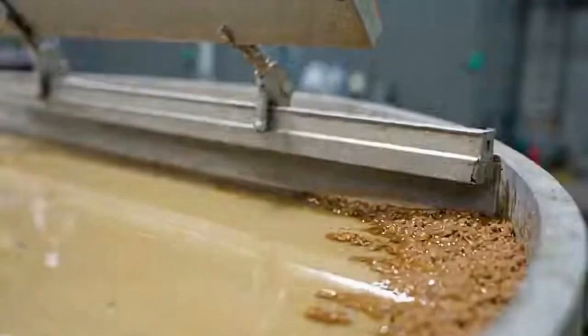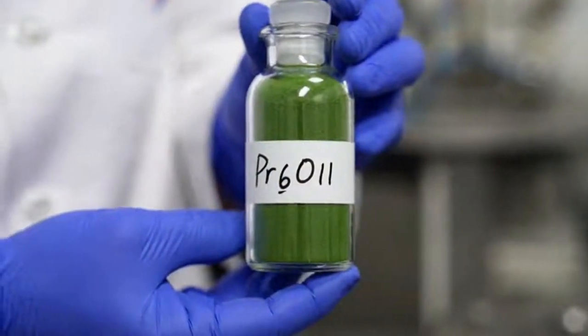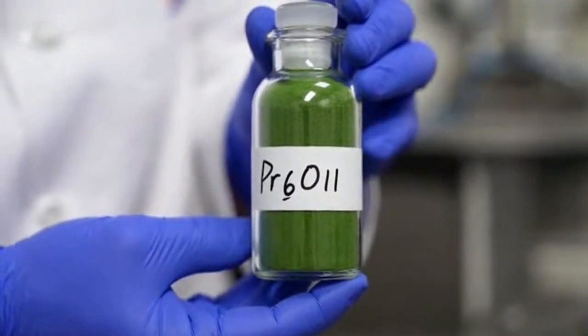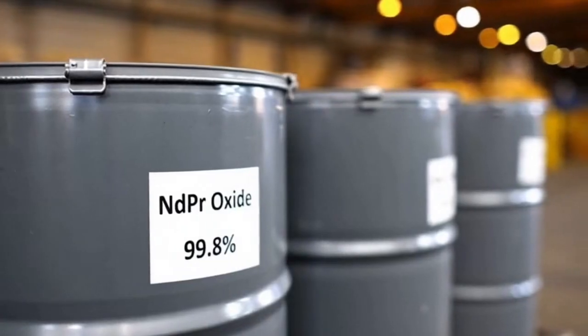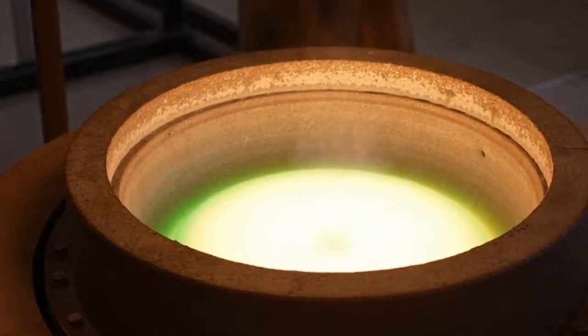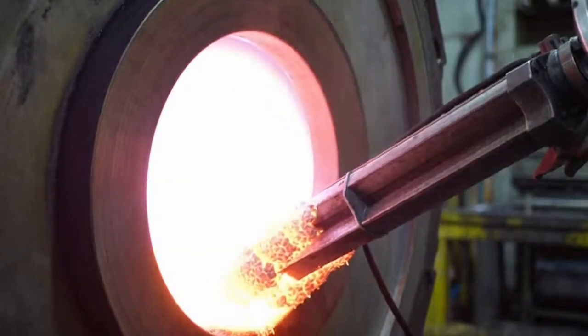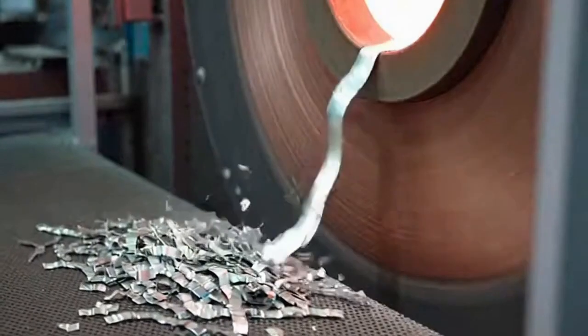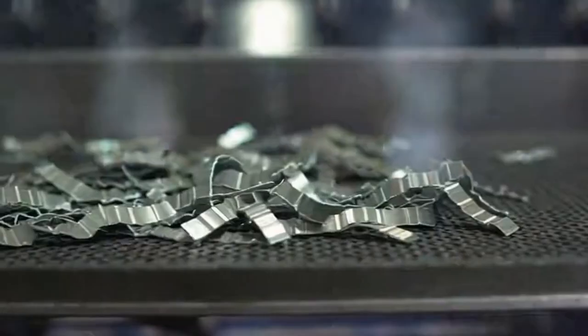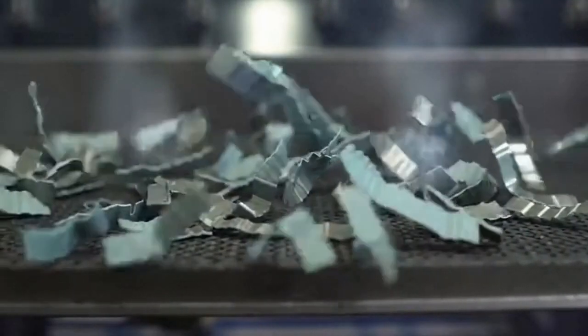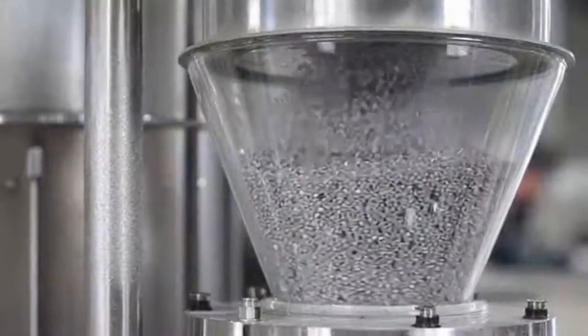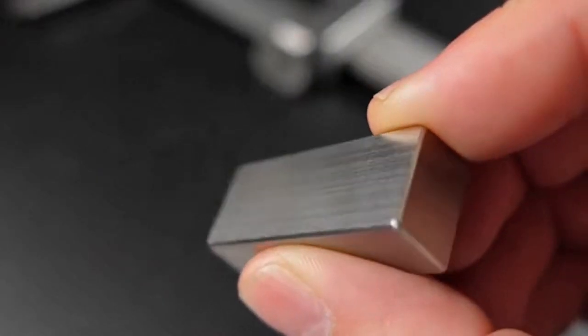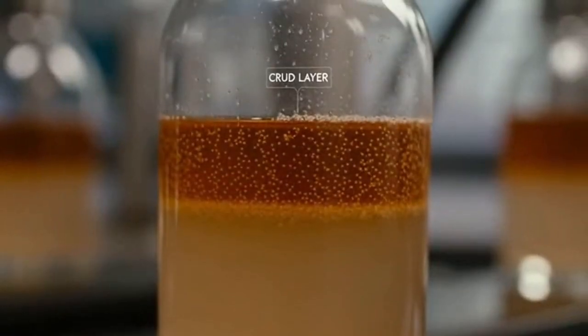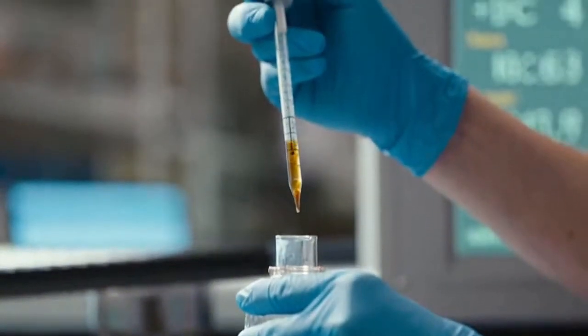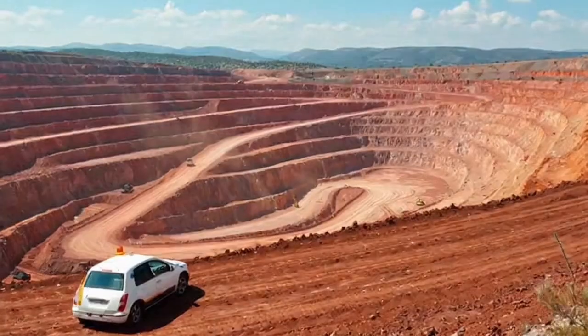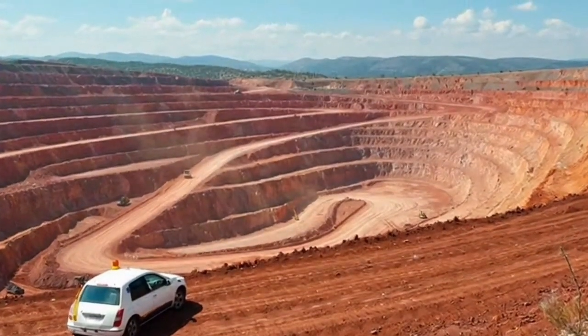If your flowsheet calls for a roast, you balance temperature so that carbon dioxide leaves briskly but the particles do not sinter into marbles that refuse to leach. If you acid bake, you watch the clock and the strength of sulfuric acid like a hawk, because too hot or too long and silica in the gangue happily becomes a gel that turns your filters into piñatas, heavy, sagging, and useless.